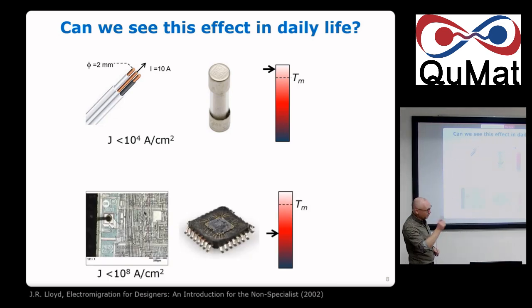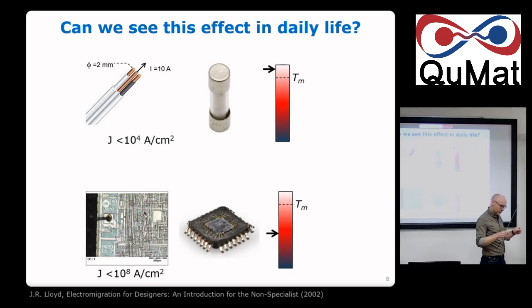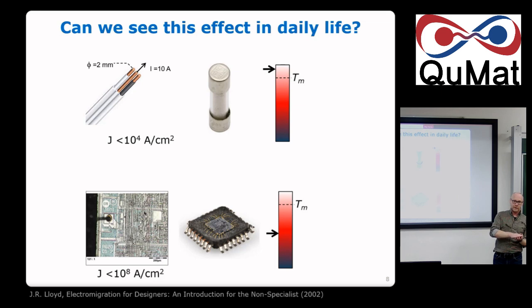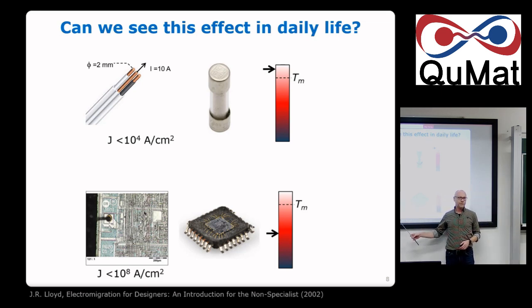Now the problem comes when you go to small dimensions, and these are integrated circuits. There, heat evacuation is very efficient, particularly because they are very small wires which are attached to a substrate. So once you heat up, the heat goes away. And in that case, you can reach currents of the order of 10 to the 8 amperes per square centimeter, which is huge, without melting the material. And at that current density, you start to move atoms.